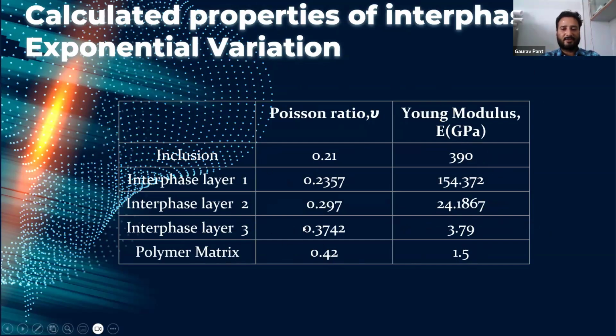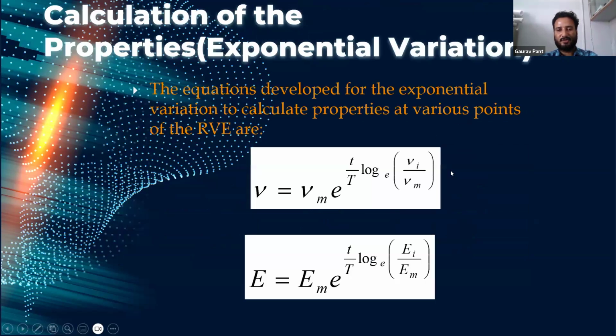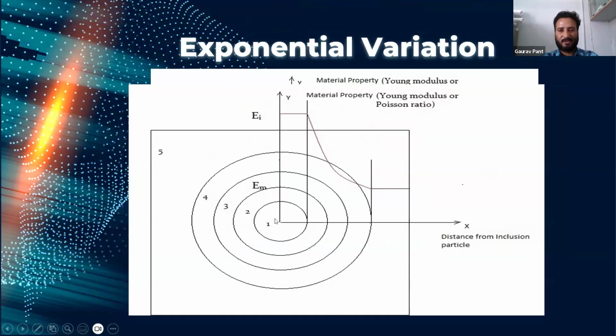In between, in the interface layers, we can see how the variation happens with this mathematical model, and what results we have obtained. This is 0.374 in layer 3, then layer 2, and layer 1. So we can see the difference. Similarly for Young's modulus, 3.79, then 24.18767, then 154 gigapascal. So this is along this direction for exponential variation.